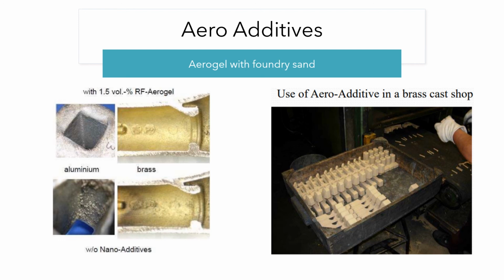As you see in the picture on the left, there are obvious improvements of the casting quality all because of using the aero additives. Above are the brass and aluminum castings with aero additives, and below are the brass and aluminum castings without aerogels. And so you can see the difference between using an aerogel in casting and not using an aerogel.